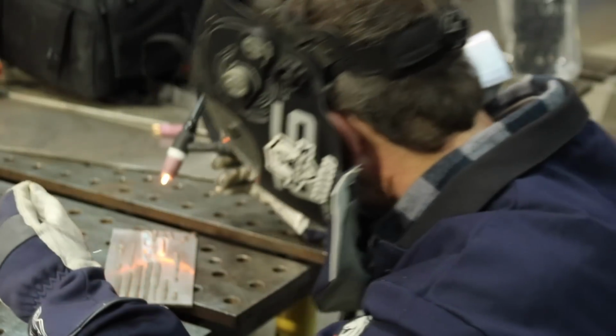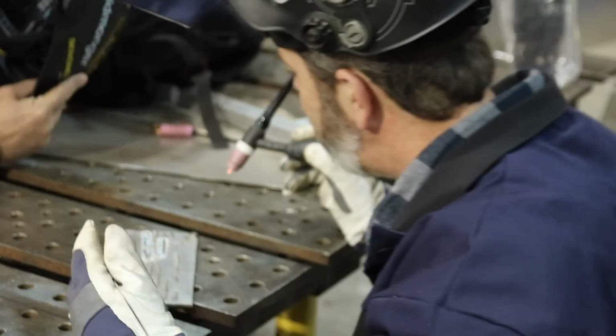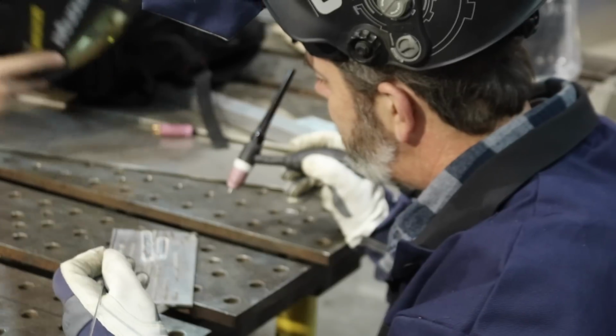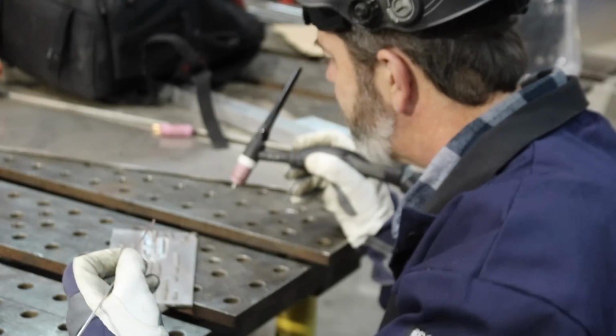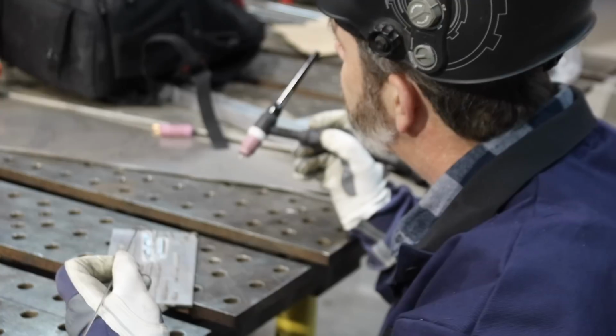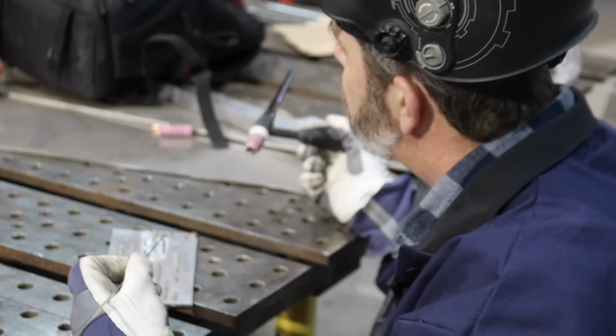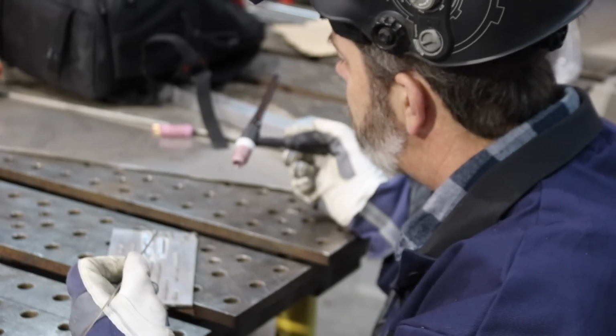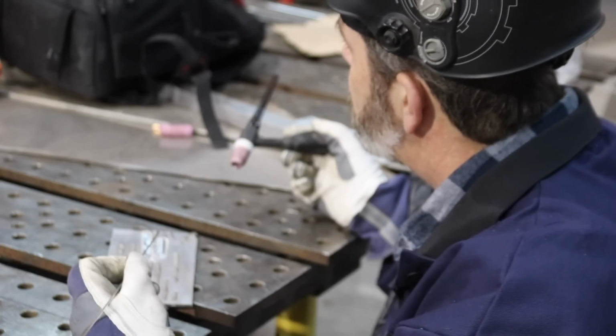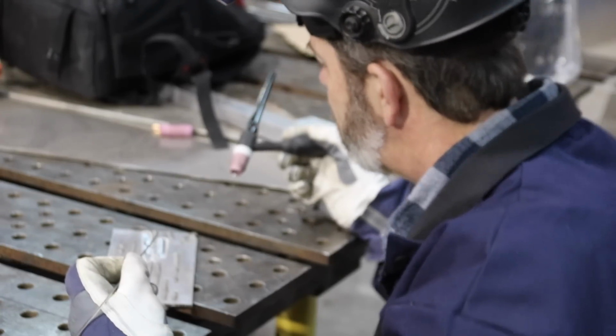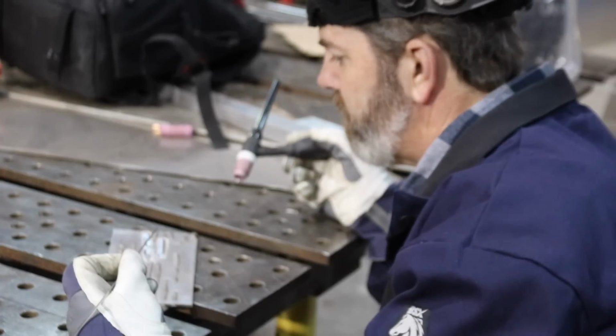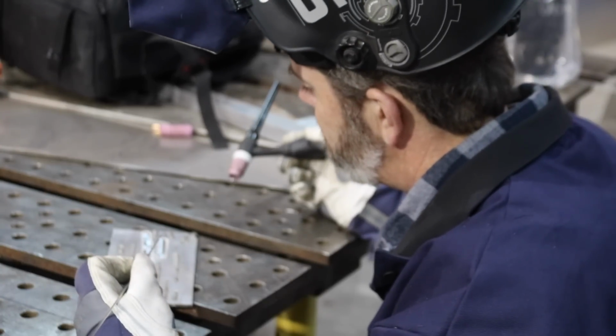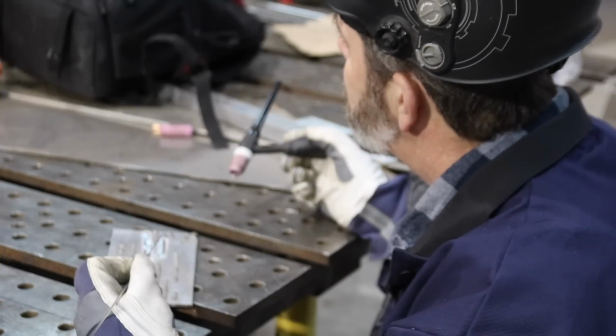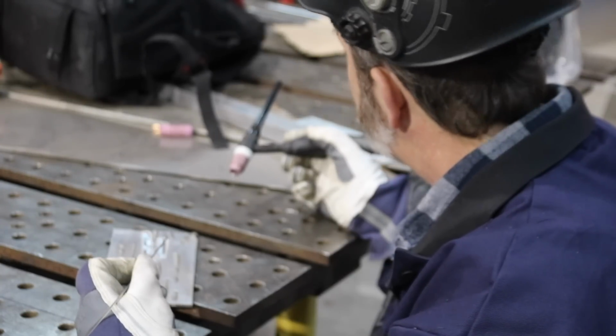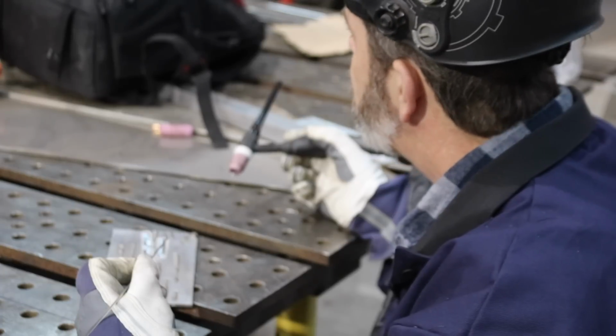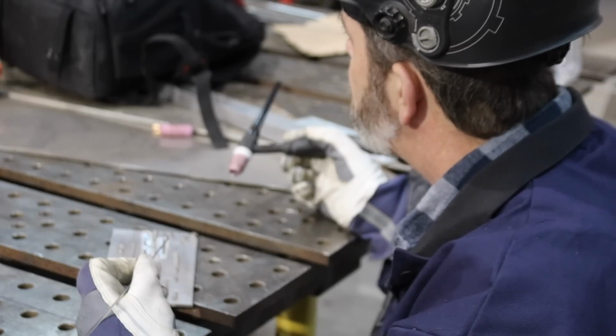Sounded pretty good. Actually, looks like a weld. So, like I said, foot pedal, it's still like steel in that once you get your amperage right, you don't do a whole lot with the foot pedal. It's a little more sensitive as far as how much you have to press to get the puddle started, especially if that piece were 4 feet wide and 3/16 thick, you would need a lot more heat, especially at the beginning.